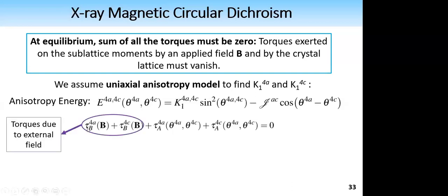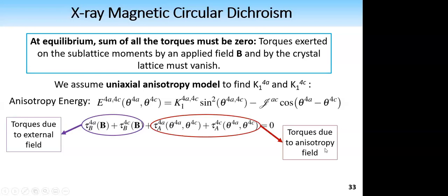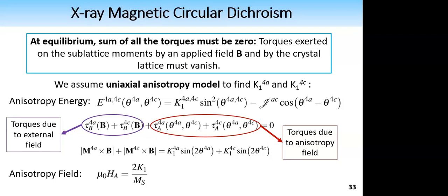On the left-hand side, I have the torques due to the external field, and then on the right-hand side, I have the torques due to the anisotropy field. That leads to the following equation that will need to be solved. You can see that I've only got 2 free parameters, which are the anisotropy constant of the 4A sublattice and the anisotropy constant for the 4C sublattice. Lastly, I can find the anisotropy field using the anisotropy constants, multiplying by 2 and dividing by saturation magnetization.